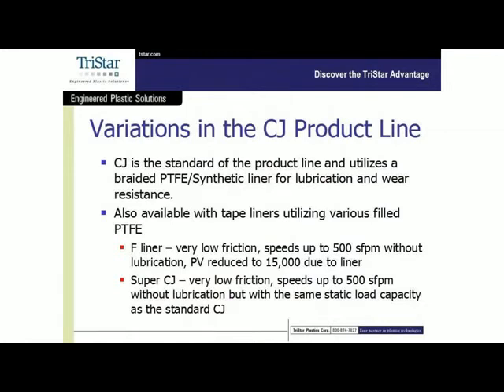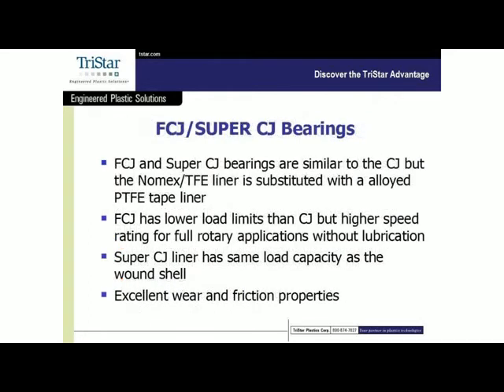Some of the variations I've mentioned to you already. The CJ is a wound sock liner. It's a PTFE and synthetic material. Those are the lubricating sources as well as an abrasion-resistant synthetic. We also have the F liner, which is a filled PTFE. That gives us a very, very low friction, speeds up to 500 feet per minute. The downside is that the PV is reduced down to 15,000 as opposed to the 25 or 35,000 with the CJ.